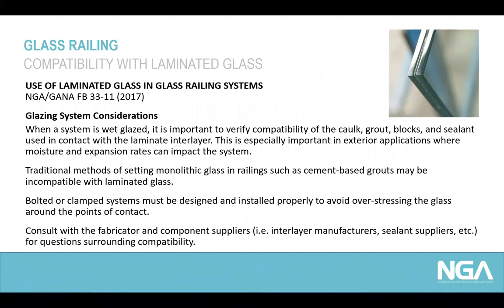And here I want to mention that section two, when a system is wet glazed, it is important to verify compatibility of the caulk, grout, blocks, and sealant used in contact with the laminate interlayer. This is especially important in exterior applications where moisture and expansion rates can impact the system. Traditional methods of setting monolithic glass in railings, such as cement-based grouts, may be incompatible with laminated glass. Bolted and clamped systems must be designed and installed properly to avoid overstressing the glass around the points of contact.